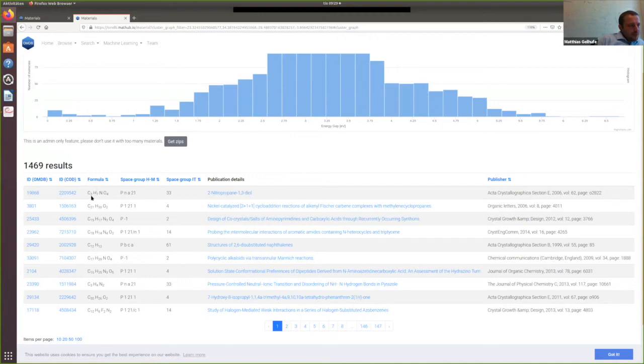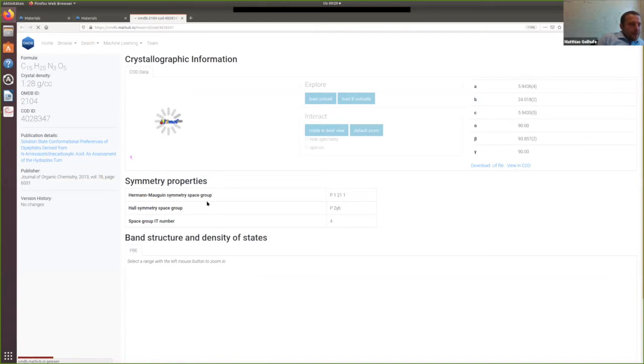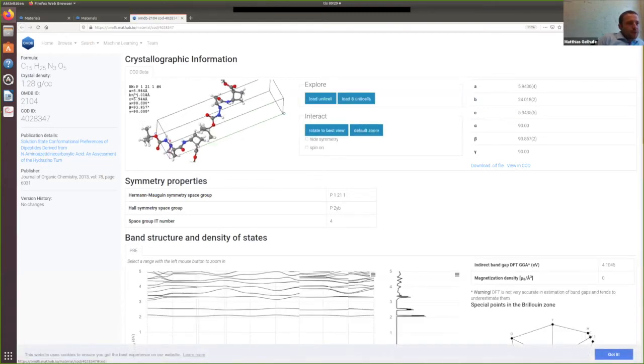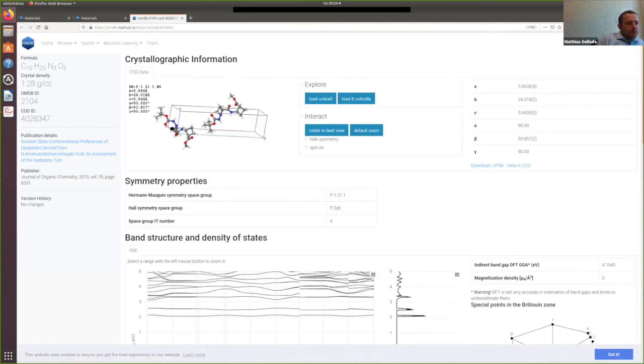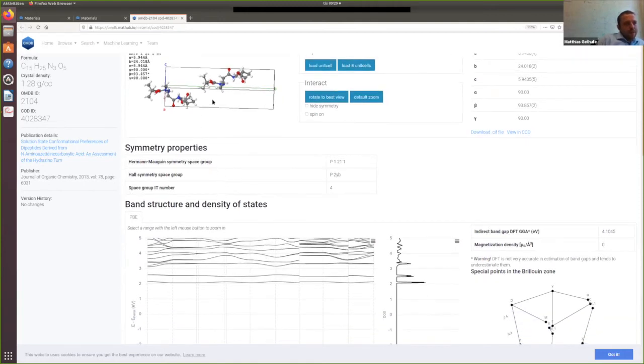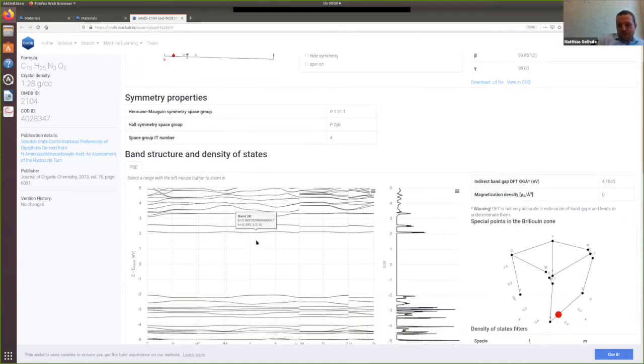And if I take a look at these materials, then I see that all of them are pure organic molecular crystals. So there are no transition metals or anything involved. It's just carbon, hydrogen, sometimes nitrogen, oxygen, maybe some fluorine or sulfur. So if I click on this material, then I see that my crystal structure is just composed of individual molecules, right? And then I can come back to the point that in these organic molecular crystals, each molecule itself is already saturated with electrons. Each molecule itself is a stable unit, and they just interact via van der Waals interaction. And there's no reason why electrons would hop from A to B. So there's no reason why this material should be metallic, right?